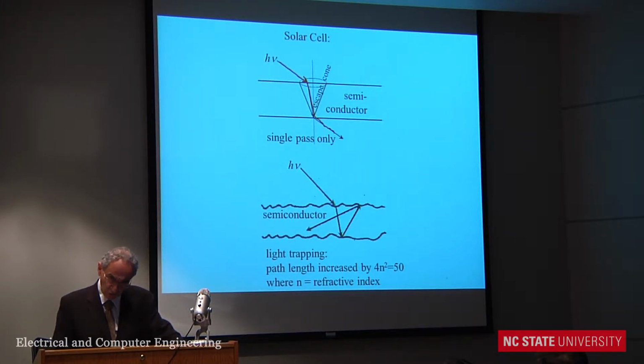And so when the light comes in, it refracts at some odd angle and does not immediately find the escape cone. And then it scatters off at some other odd angle because the surface is rough. And before you know it, it has no memory of the original angle it went in at, and it's at a random angle, trying to find this very narrow escape cone. Now, the refractive index of most semiconductors is 3.5. Very different from glass, which is 1.5. That's a huge refractive index. And so this escape cone is extremely narrow, maybe 14 degrees. So it bounces around an awful lot before it ever escapes.